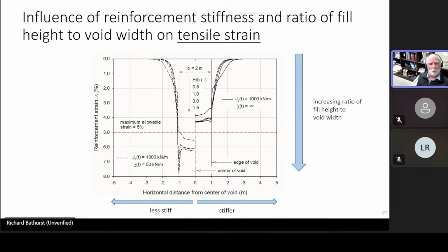Here you see a slide in which we have, again, stiff reinforcement, less stiff reinforcement, but what we have varied here is the ratio of the height of the fill to the width of the void. And it's interesting, you can see that it really doesn't have a major effect on the reinforcement strains. But again, the strains are much higher for the softer cases. And you can see that, again, the maximum strains are at the edge of the void.